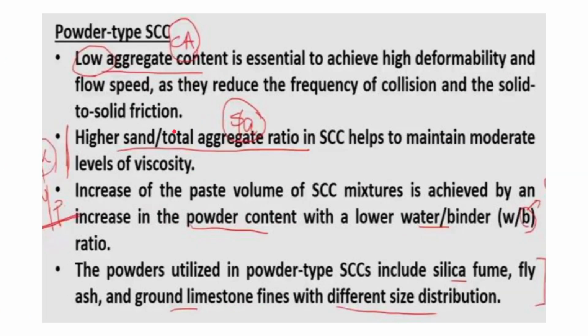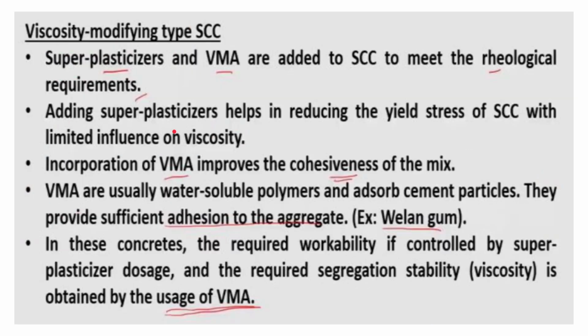Now let us go into viscosity modifying agent, VMA, type SCC. Superplasticizers and VMA are added to SCC to meet the rheological requirements. In the earlier type, superplasticizer and powder were used, powder basically meaning mineral admixture, and here superplasticizer and VMA are used. Adding superplasticizers helps in reducing the yield stress of SCC with limited influence on viscosity, because superplasticizers increase the workability, so they reduce the yield stress, and have very limited influence on viscosity.